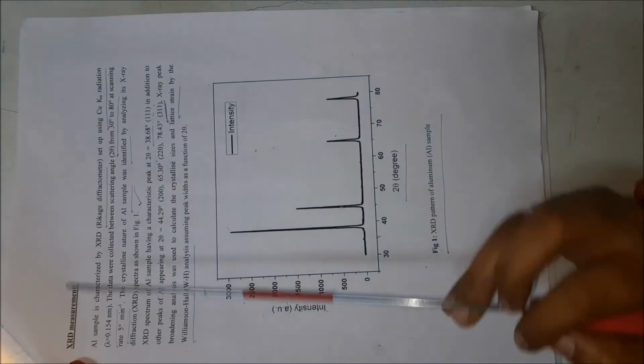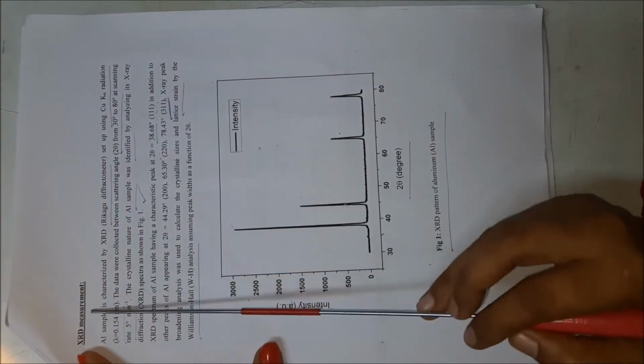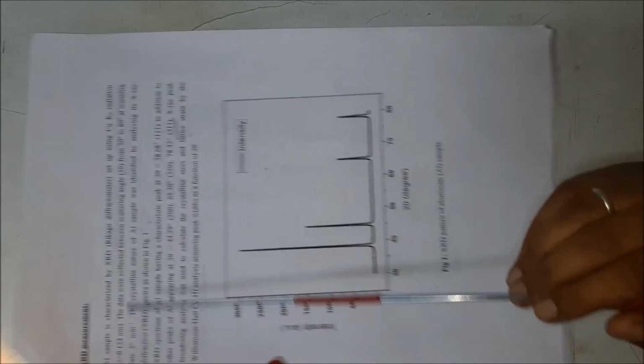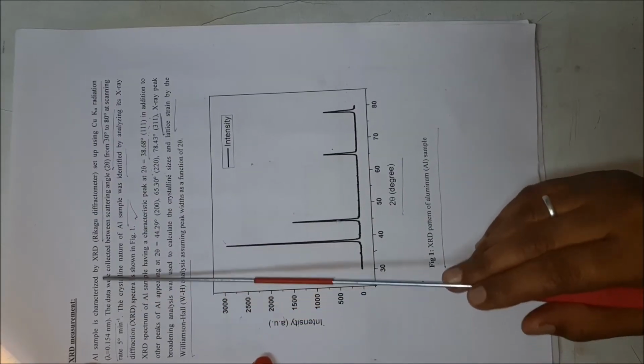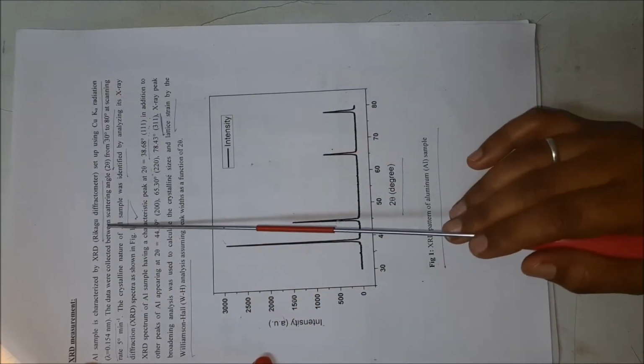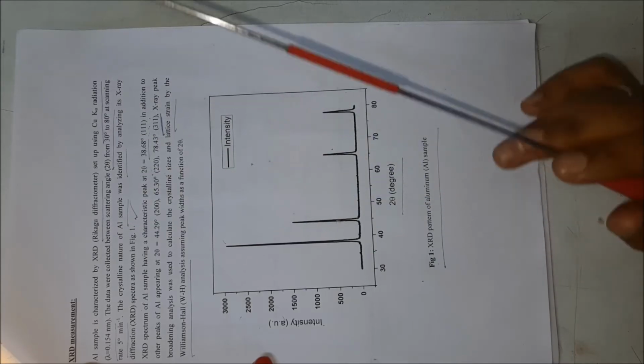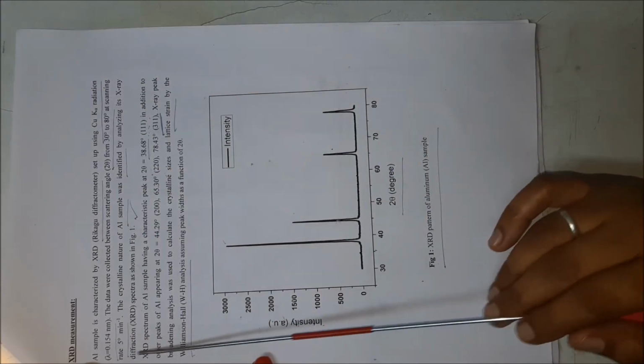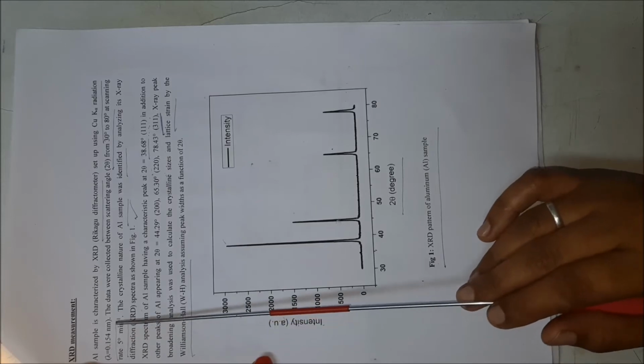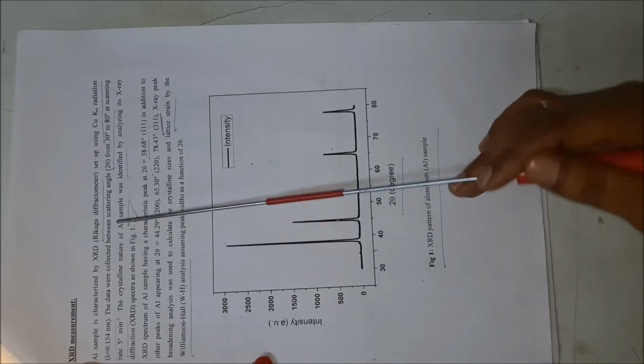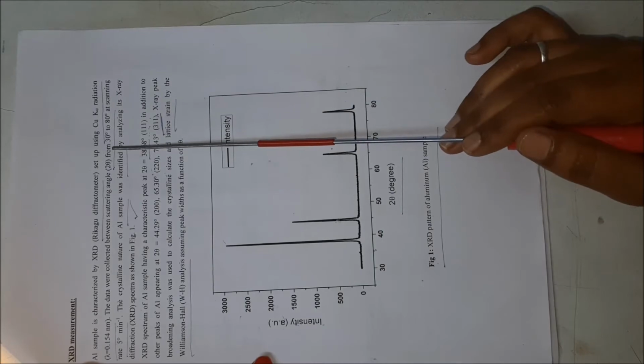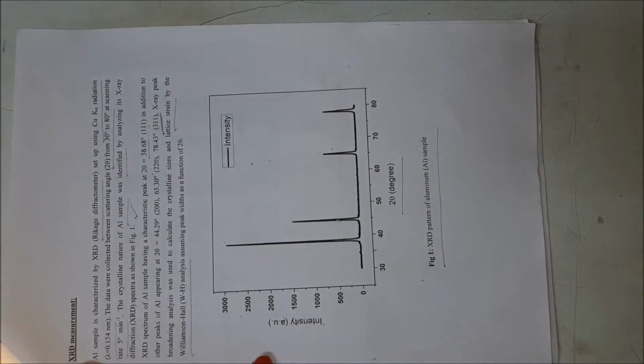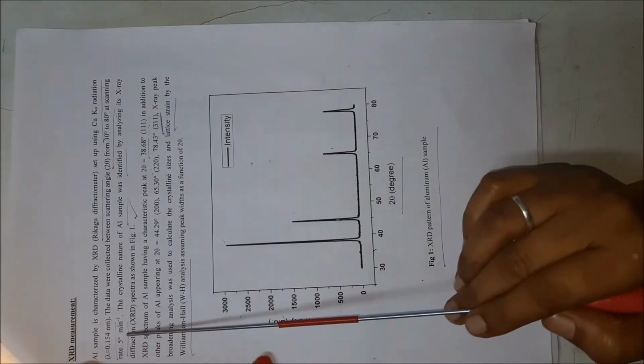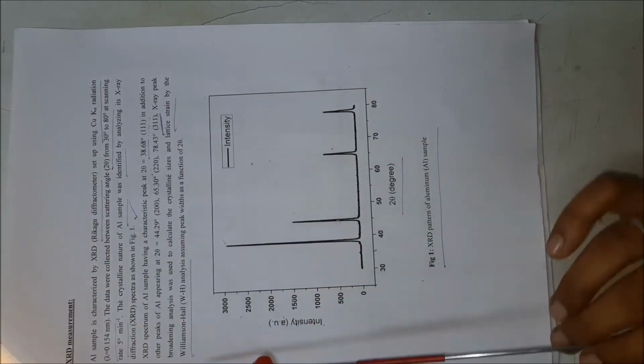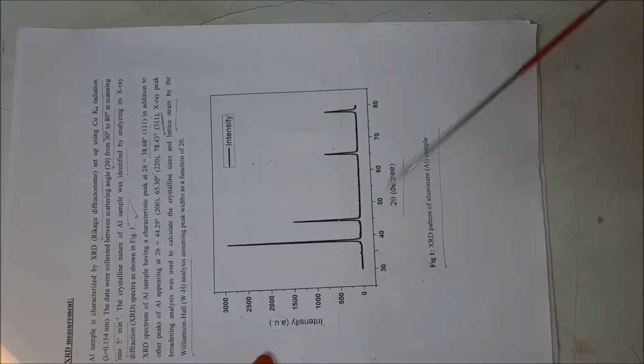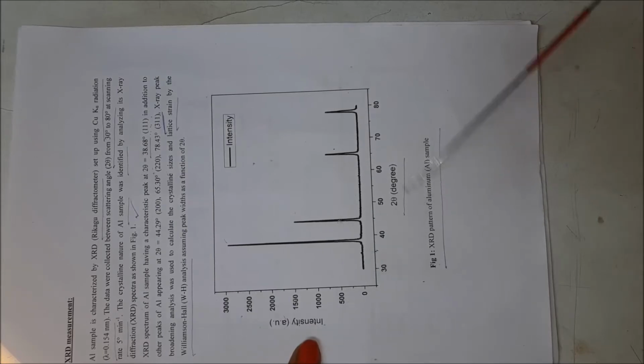Now, we can discuss the XRD measurement. The aluminum sample is characterized by a Rigaku XRD diffractometer setup using Cu K alpha radiation, where lambda is 1.54 angstrom. The data were collected between scattering angles 2 theta from 30 degrees to 80 degrees at a scanning rate of 5 degrees per minute. Now, a graph is drawn between intensity versus 2 theta.